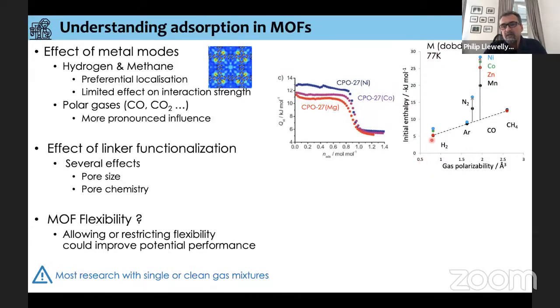So going from hydrogen down here up to methane on the right-hand side, we can see that the initial enthalpy of adsorption for methane, when we vary the metal centers, doesn't change too much. And I've drawn a straight line between the methane and the nitrogen. But what is interesting, for example, with carbon monoxide and nitrogen, is that we move away from this straight line, which means that there is a preferential interaction of, for example, carbon monoxide with its dipole with the metal center.